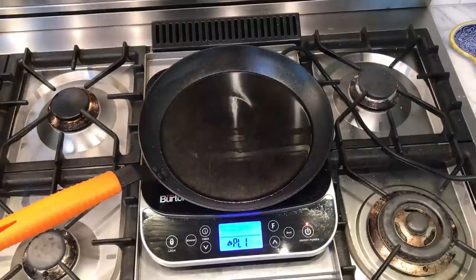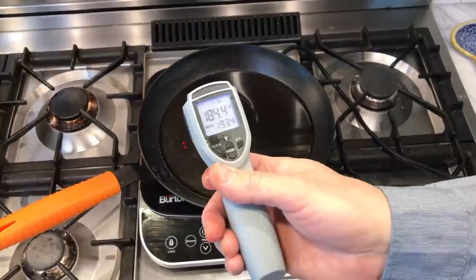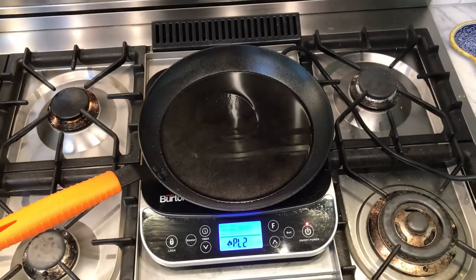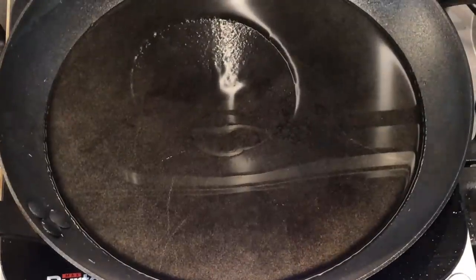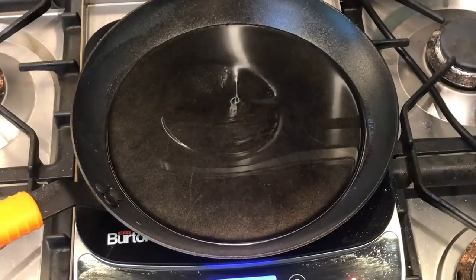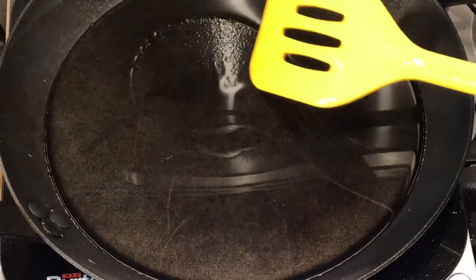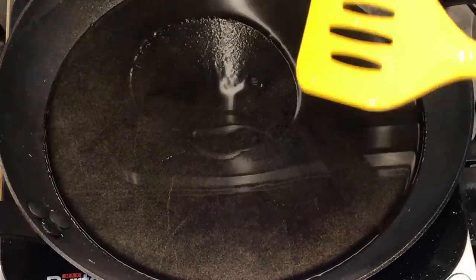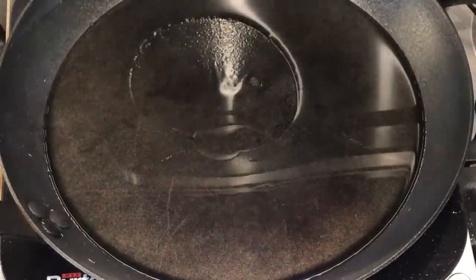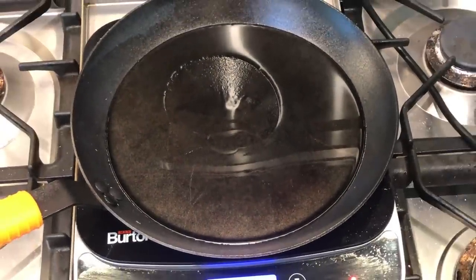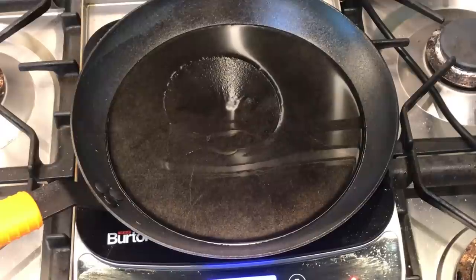So I used a little bit of extra oil so I could see if that island really did develop, and in fact it did. As this pan heated up on the induction burner, that bow that Lodge puts in the bottom of the pan seemed to give me almost inverse warping. The pan didn't seem to flatten at all, and in fact, the bow expanded and I have a little bare metal island and a little C-ring of oil.